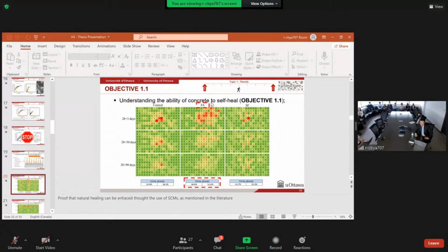Replacing 30% of the cement by fly ash class F, we were able to enhance this value to 50%. However, once we use 10% of silica fume, this number decreased in comparison with the control specimen. So the faster reactivity of the silica fume, and also the lower volume of silica fume in the mixtures, seems to decrease the ability to self-heal in the concrete. I think I got it. So I think what you're saying is the silica fume was consumed. It's consumed faster up to 28 days, and after 28 days, it seems that we have less unhydrated particles to contribute in the healing process. Yeah, no, that makes sense.